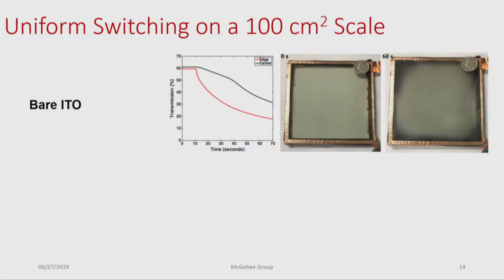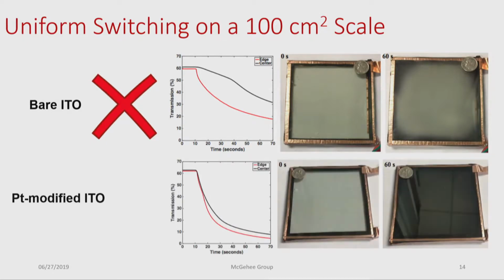So when we want to translate this from a 3-electrode half-cell into an actual 2-electrode device, you can see that where we failed initially on a bare ITO surface to plate uniformly, now with the platinum modification, we're able to switch uniformly on a 100 centimeter squared scale.